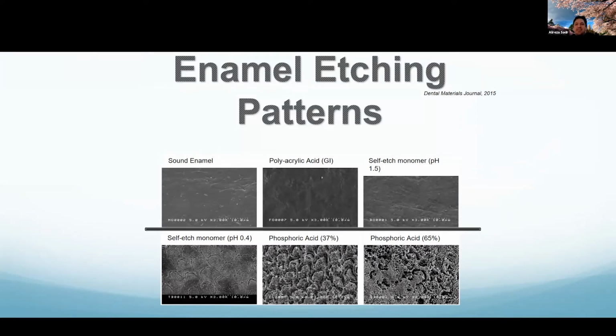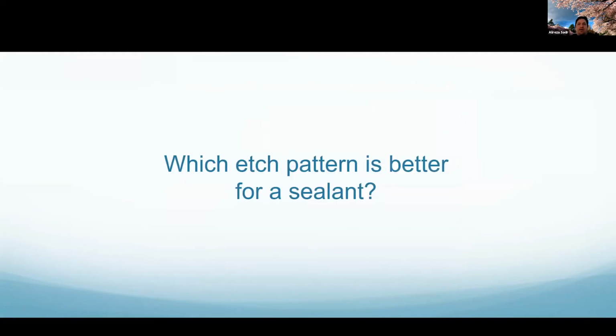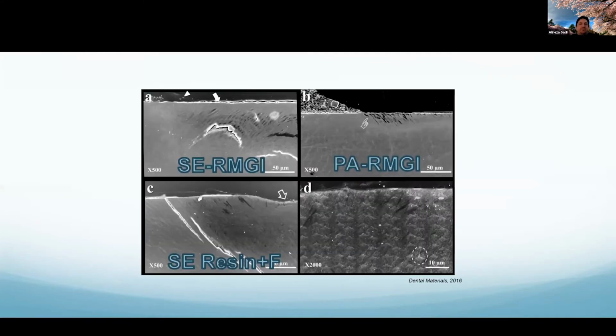So that's another thing, another issue that I have with resin-based sealants. So minimally invasive dentistry, look at what the polyacrylic acid can do there, look at what your air abrasion is going to give you, and then probably stay away from more damage to the enamel. Don't have a lot of evidence on that right now, but I have seen the hypermineralized layer of enamel being removed by phosphoric acid etching. For application of a sealant, that might be a little bit too aggressive.